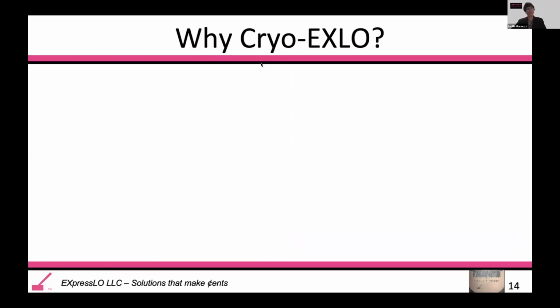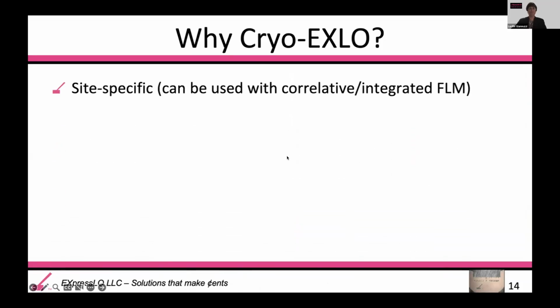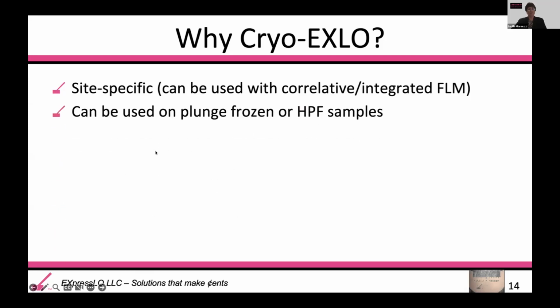So let me continue on then, and that gives you a little bit of background of what ex situ lift out is and how it can be used. So why would this be beneficial for cryo ex situ lift out? Obviously, we're doing lift out just like any other FIB technique. And again, this technique is FIB agnostic, so you can use any FIB and any TEM since this is done outside of the FIB. There's no reason why it can't be used with correlative microscopy as well. It can be used on plunge frozen or high pressure frozen samples.